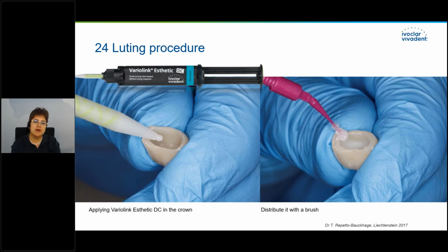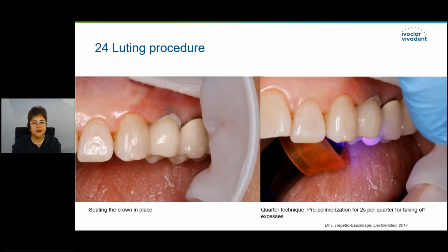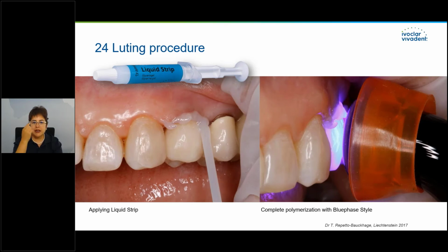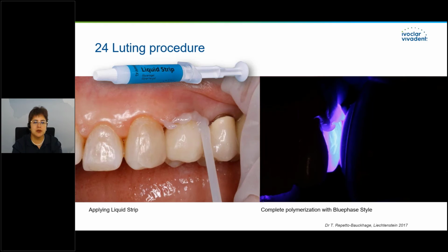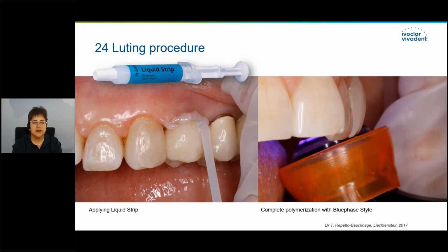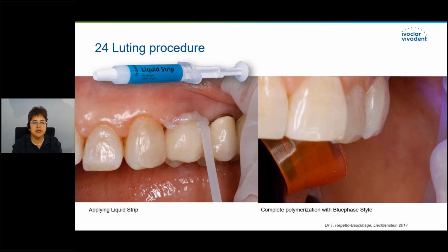So afterwards, we apply Variolink Esthetic DC in the inner part of the restoration, and we spread it with a micro brush. Then after seating the crown, we do the pre-polymerization per quadrant. So 2 seconds off, 2 seconds off, 2 seconds off in the different ways. Then I applied Liquid Strip, our glycerin gel, and I polymerized through the crown, then the final part also from occlusal and from mesial.